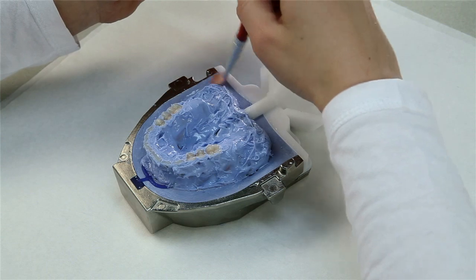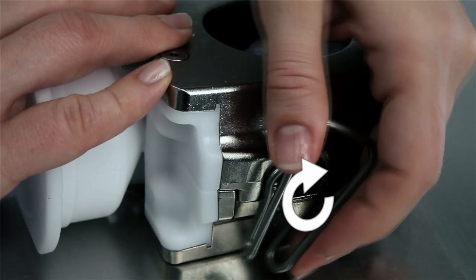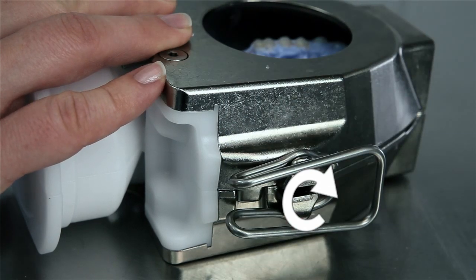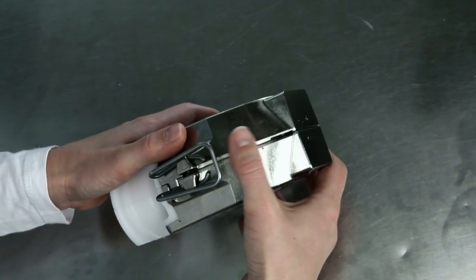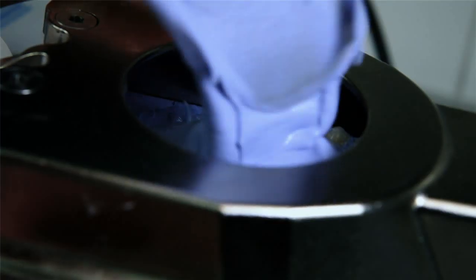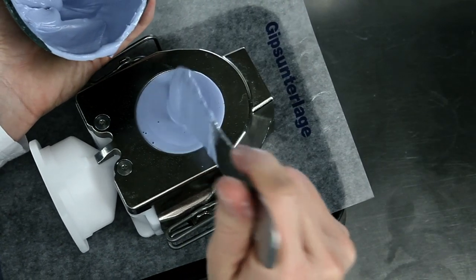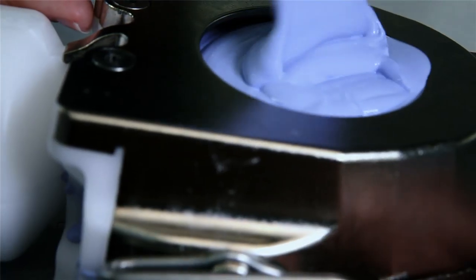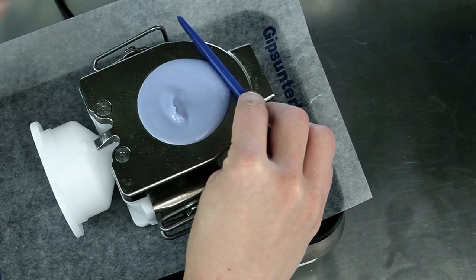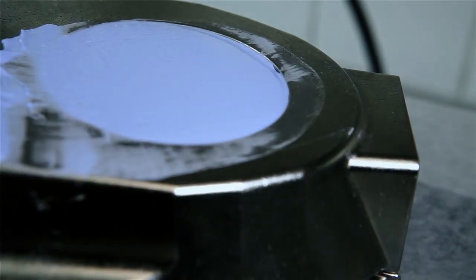After that, isolate the stone-to-stone contact surfaces. Now lock the two flask halves using the locking clasps. Make sure that the flask edge is clean. Allow the mixed class 3 stone to flow into the opening of the flask on a shaker until the flask is completely filled. Prevent air from being trapped in the material. Skim off the excess stone using the IvoBase spatula so that no stone protrudes from the flask opening.